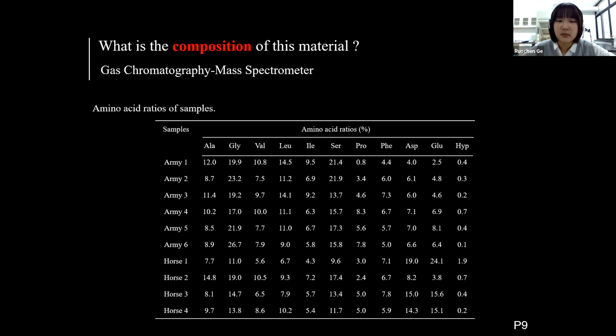Amino acid ratios in samples are listed in this table. Hydroxyproline, the characteristic amino acid of animal glue, was detected in all samples and even reached 1.9% in Horse 1. The average ratio of glycine in all samples is 18.64% and is very close to 20% from Army 1 to Army 6. These glycine ratios are the same as that of the animal glue, indicating the presence of animal glue in all